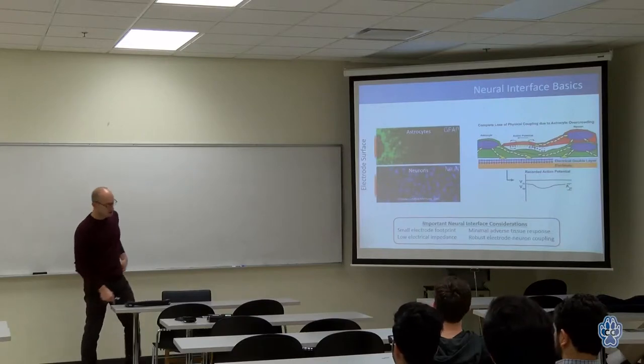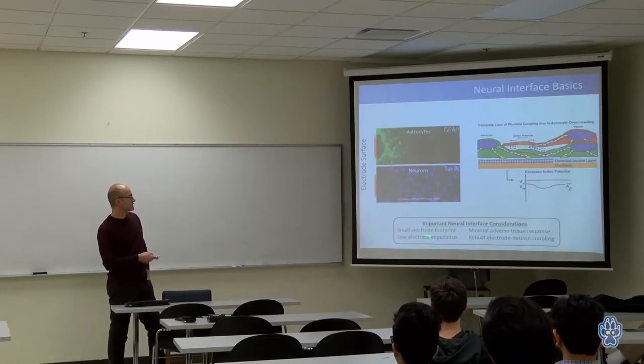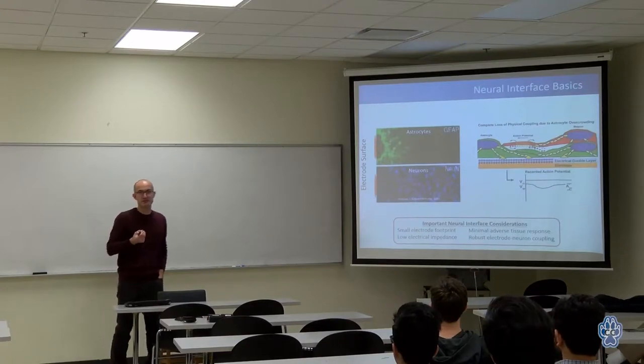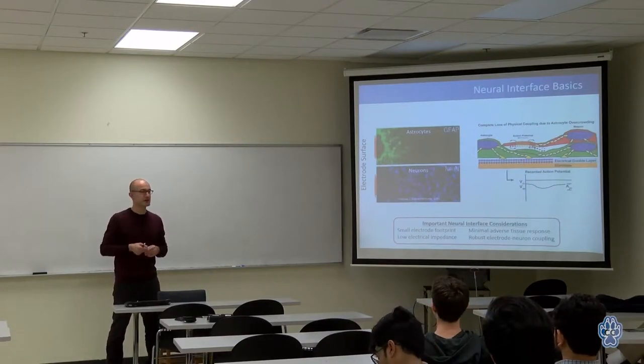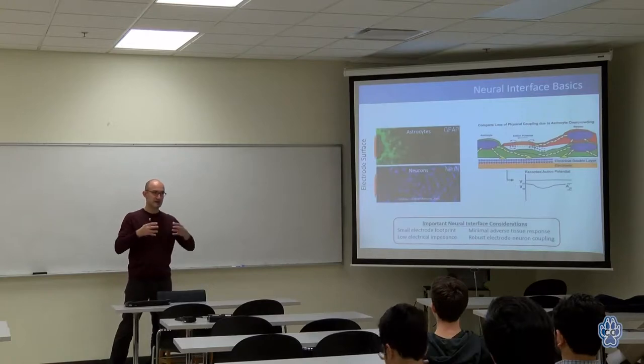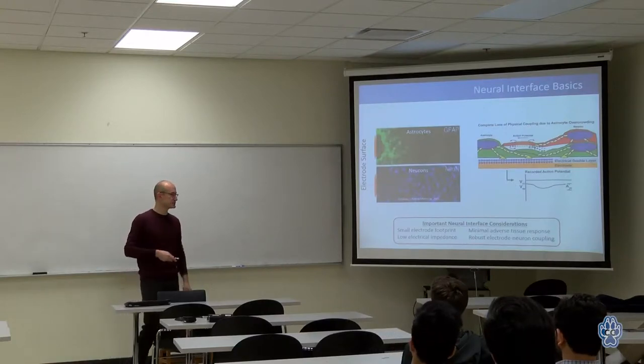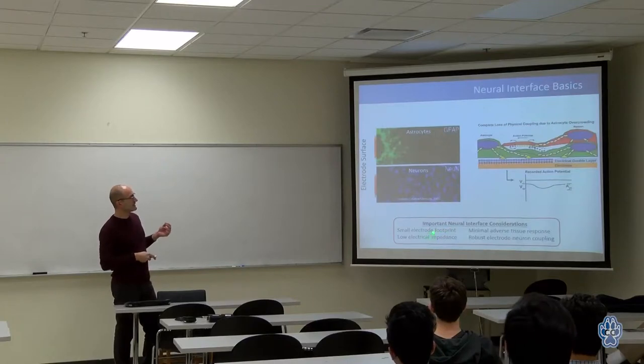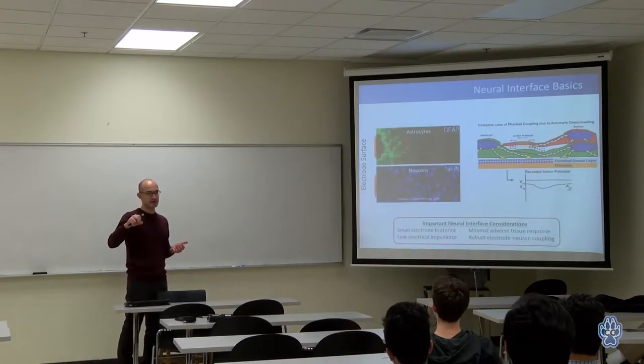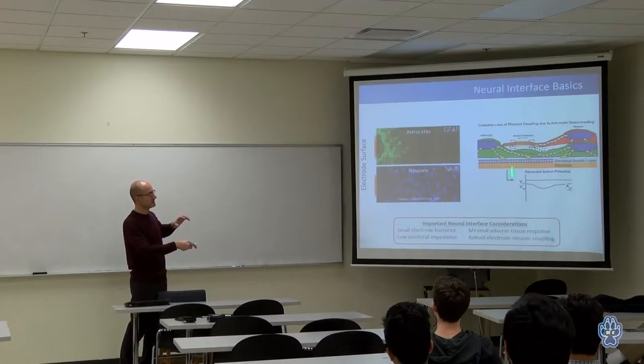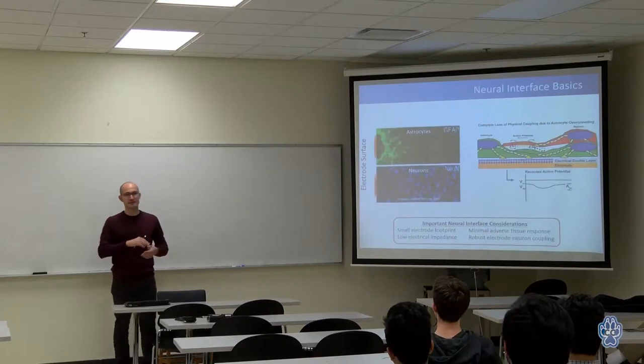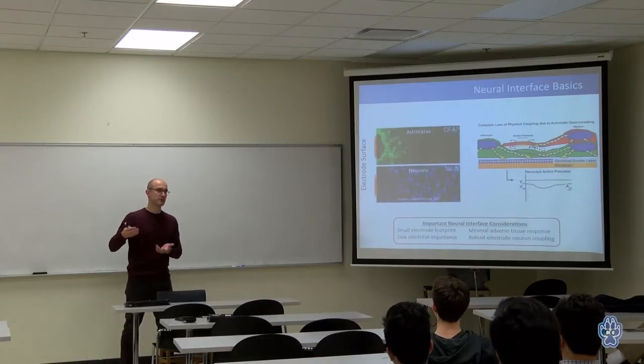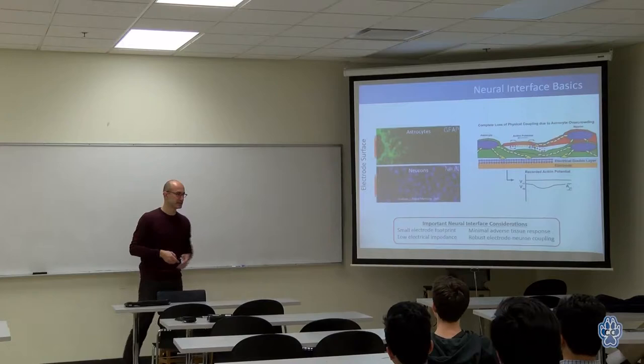Exactly. The important considerations are, you want a small electrode footprint. Similar to a digital camera, if you have smaller electrodes that are more densely packed, you have higher spatial resolution. But you also want low electrical impedance. From instrumentation theory, if the impedance of the electrode is low and it's connected to an instrumentation amplifier, you can pick up these voltage changes with much higher SNR. If the impedance is very high, then you are picking up the thermal noise from the instrumentation and you are not really getting your signal.